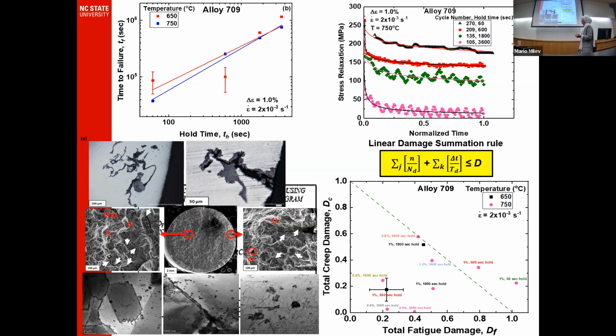We also look under the transmission electron microscope at the dislocations and precipitates. Under creep fatigue damage, we observe subgrains and chromium-rich precipitates. We also observe well-organized boundaries with network dislocations, unlike what we observe under pure fatigue tests, which shows disorganized boundaries with tangled dislocations.